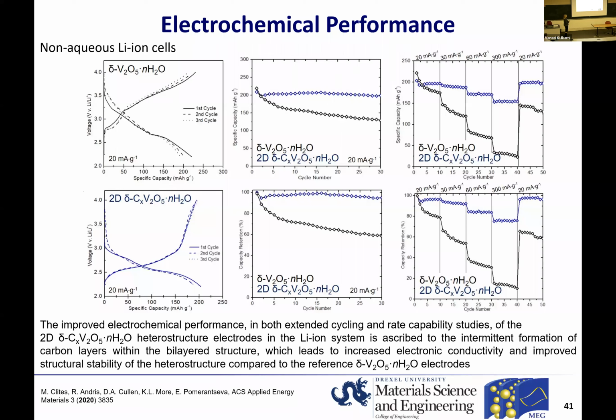So this heterointerface material shows much improved stability, but even more exciting, look how much better the rate capability is. The drop when we increase current density is much, much smaller compared to the pristine bilayered vanadium oxide electrode. This basically tells us that the charge transfer processes are improved, and we attribute it to the formation of the carbon layer in the interlayer region of bilayered vanadium oxide. So with this method, we were able to achieve that.